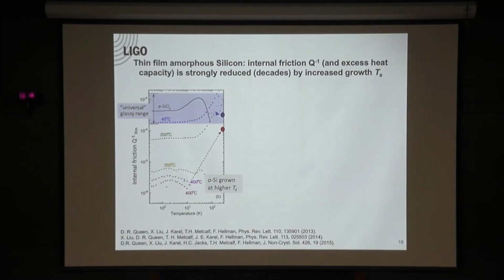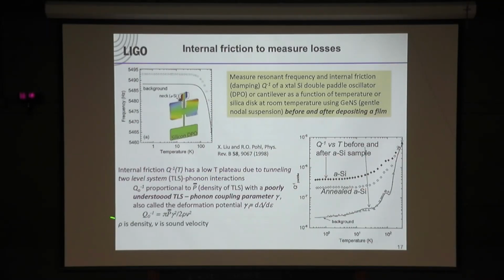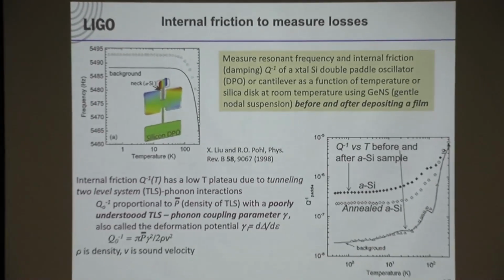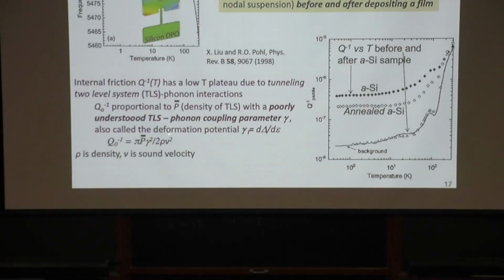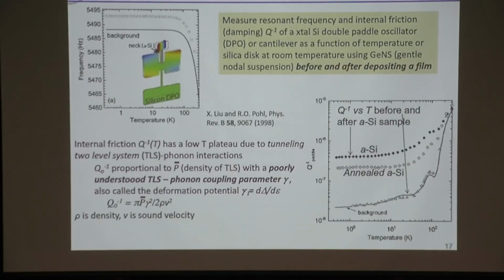I somewhere have that equation, I thought, but, well, I'm not going to find... Oh, yeah, there it is. That is actually the equation. It's a fairly simple equation. P bar is the tunneling level states density, which is a density not in real space, but in energy space. Rho is just the atomic density, that's easy. V is the sound velocity, that's easy. But there is this gamma, and gamma is known as the deformation potential. It is also the TLS phonon coupling parameter. Those are the same thing if you work through the math.